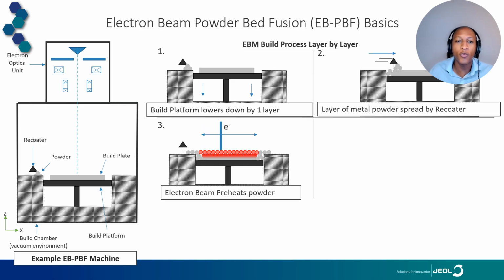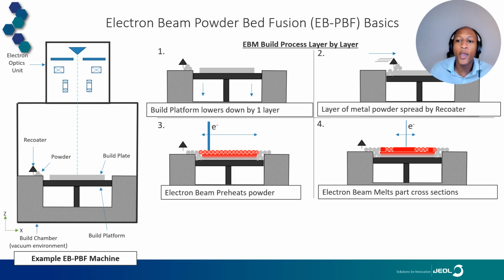And by doing so, we not only increase the temperature of the powder bed, but we also sinter those powder particles together. After which, on step 4, we actually melt those cross sections via a typical contour and hatch scan strategy in order to weld those powder particles together and create our layer. From there, we repeat this process back to step 1, and we repeat that process layer to layer until we have our full part.